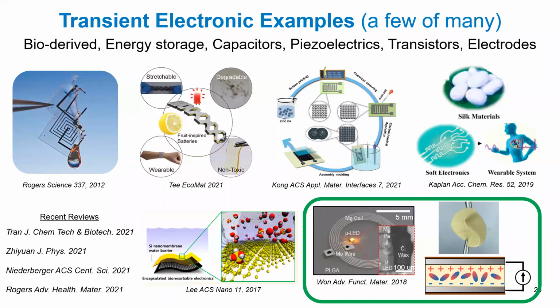That's the gold standard. And there are inherently issues with using magnesium that will need to be worked out as well. But the problem is really the encapsulation material. Because if you are using a polymer that's soft and flexible, then the permeability, the diffusion of water through the film, is going to be much higher.